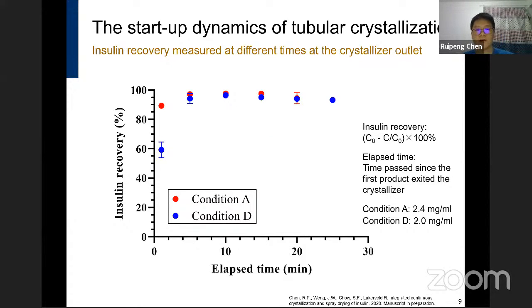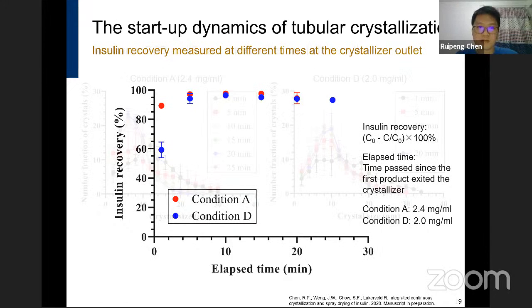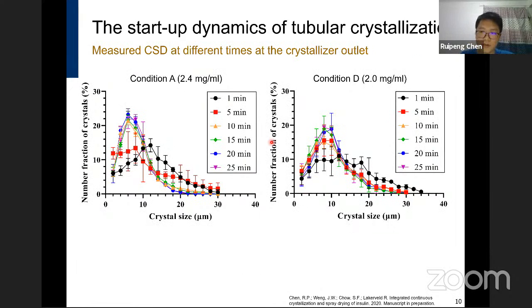And then we can look at the CSD at the crystallizer outlet for these two conditions. The trend is similar to the insulin recovery. For both conditions, the CSDs were on the right at the very beginning, and then start to shift to the left. Condition A and condition D reached an approximate plateau in around 10 and 15 minutes, which is slightly later compared to the insulin recovery. The condition A with a higher initial concentration reached the plateau faster compared to condition D.